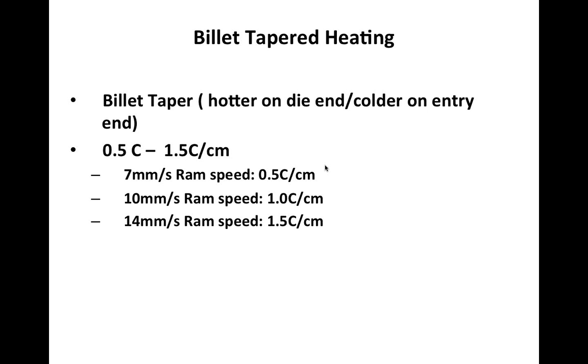If we vary our ram speed very much, we're also going to be changing the deflection of the die and the opening in the aperture, which is going to change our shape and wall thickness and speed of aluminum flow through the die. So it's virtually impossible today to have isothermal extrusion with 100% ram speed control. So the only other way to do it is to taper heat the billet. And I just saw we just did it in Celsius instead of Kelvin.